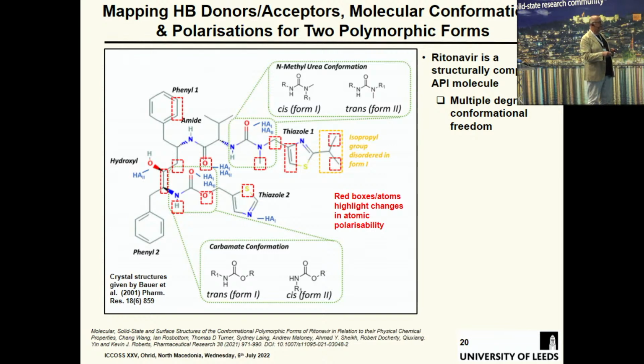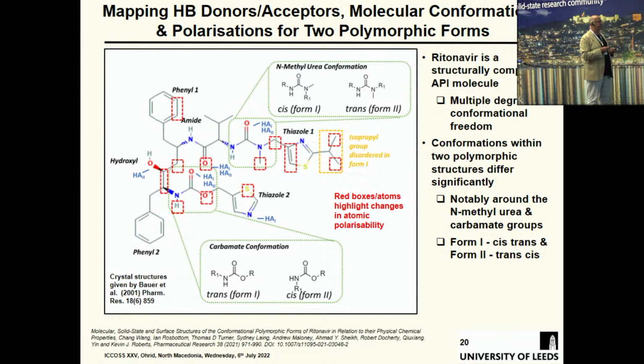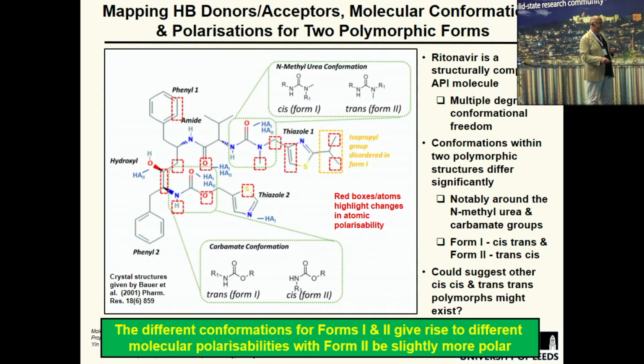So these red boxes show the atoms that undergo a reasonable amount of change from the conformation. And the conformation's quite radical in this molecule. So conformations within the two polymorphic structures differ significantly, notably around those groups. As I say, form 1 is cis-trans, form 2 is trans-cis. And that could suggest that there are other polymorphs, particularly cis-cis and trans-trans, still to find, for those interested in structure predictions for chiral molecules. The different conformations of form 1 and 2 give rise to different molecular polarizabilities, with form 2 being slightly more polar.